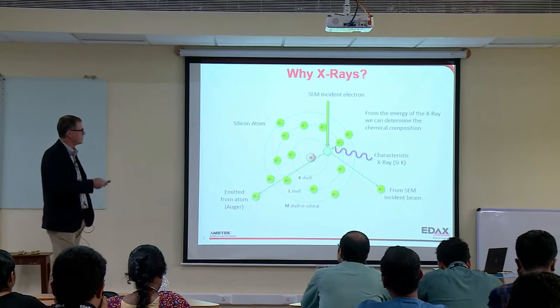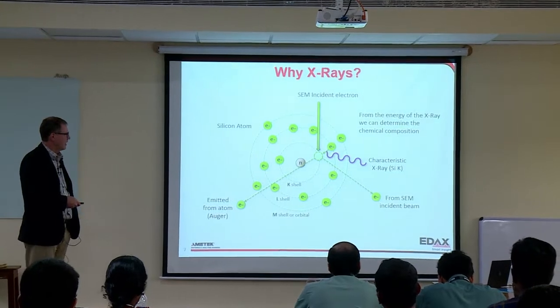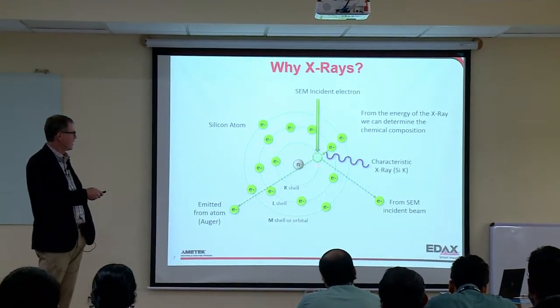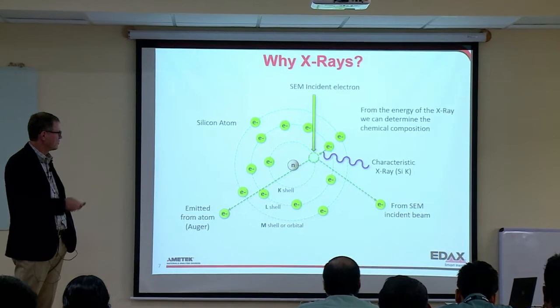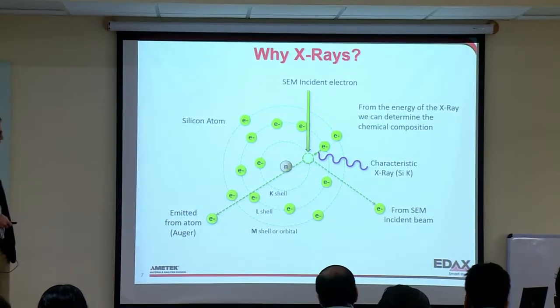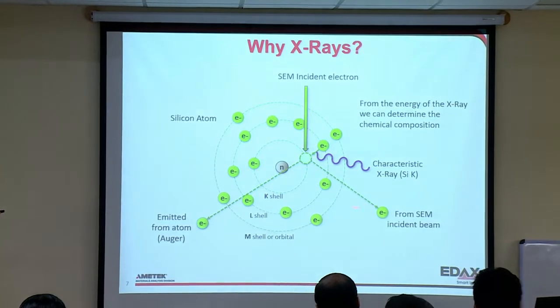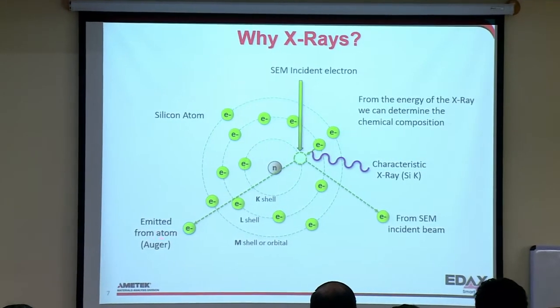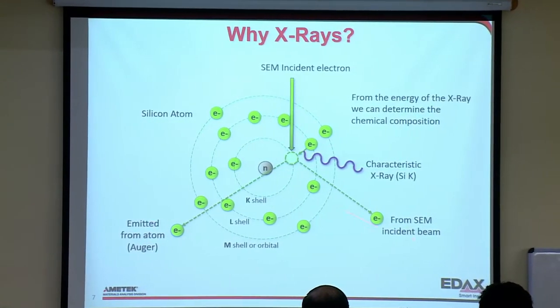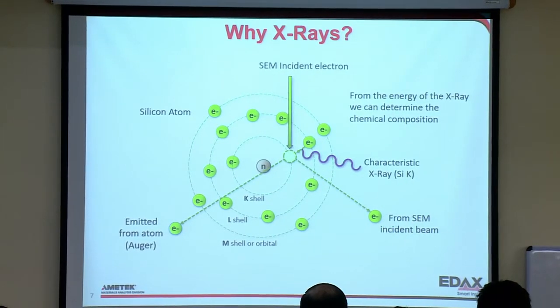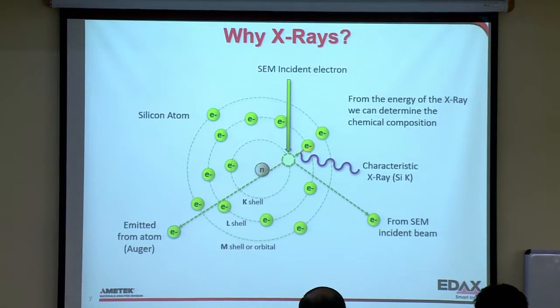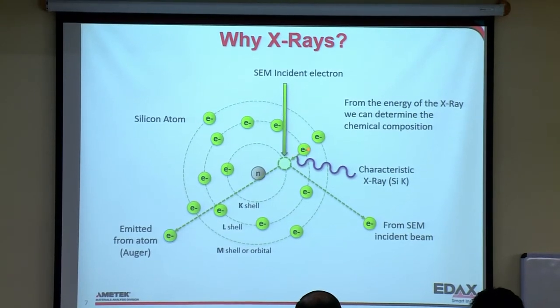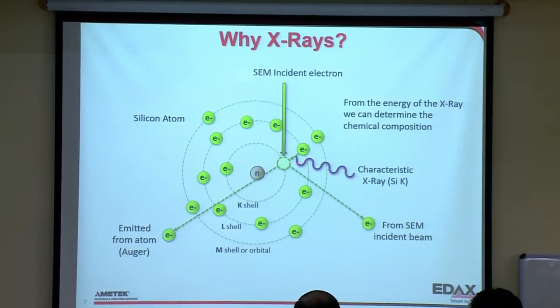So why do we get X-rays? Well, the electron comes in, and what it does is it knocks an electron from the atomic structure, from the atom. And so you can get an electron emitted from the atom, which is the Auger electrons. From the SEM, you get the incident beam reaction. But because you have a movement here of one electron moving down to another shell, from the L shell to the K shell in this example, you get a characteristic X-ray. And so this information we can capture in the SEM.